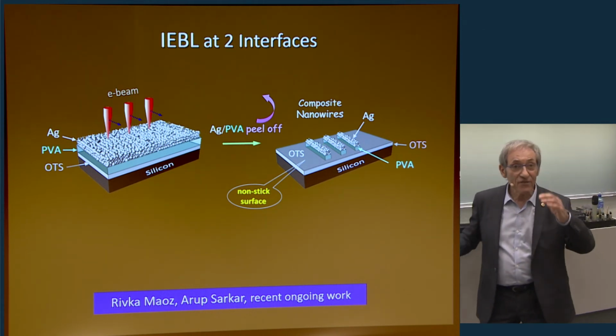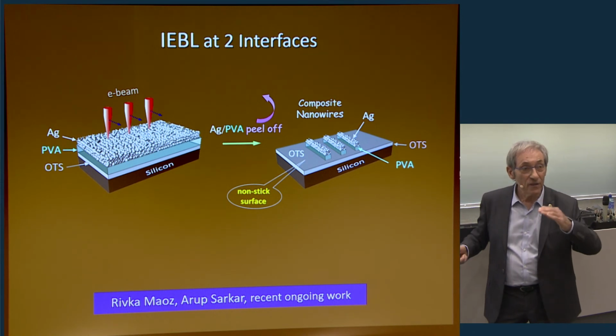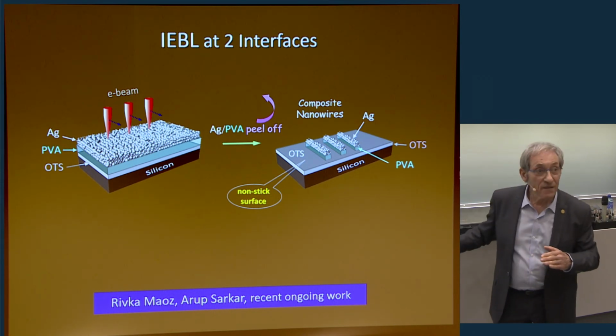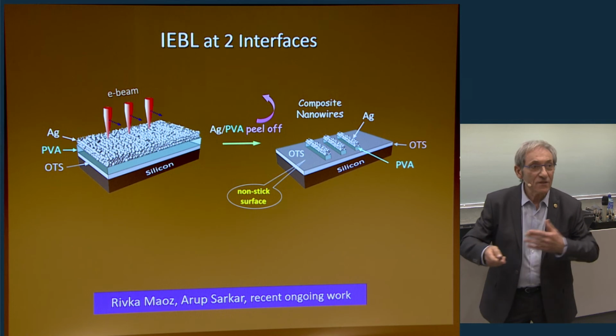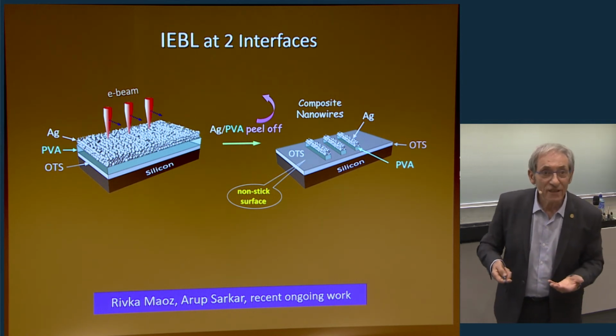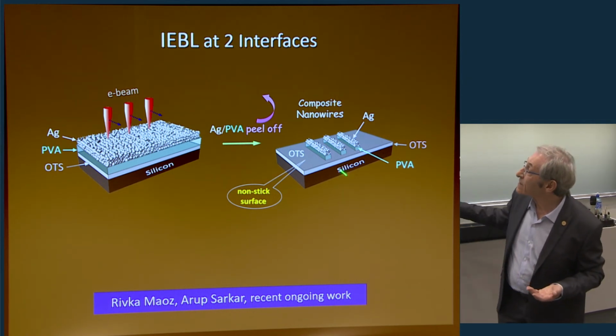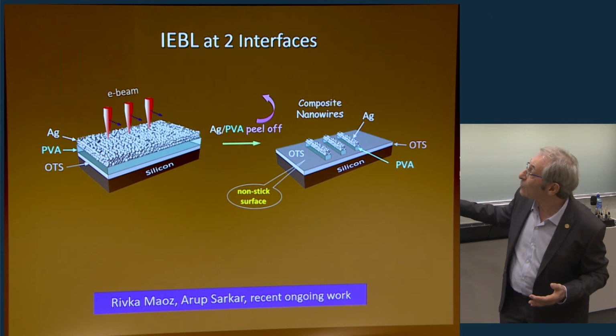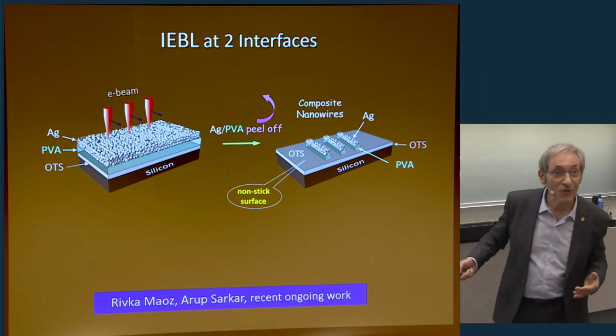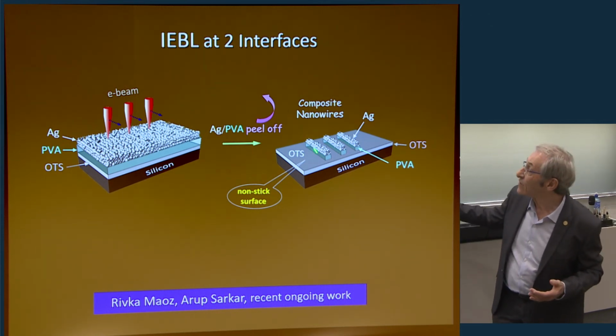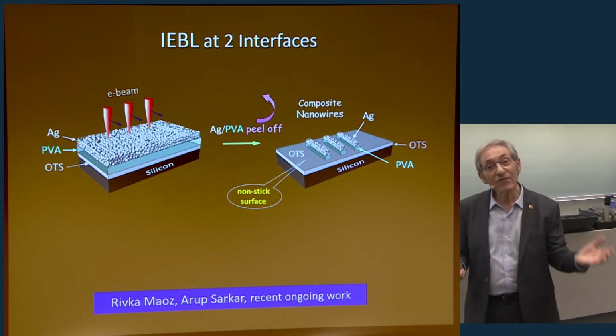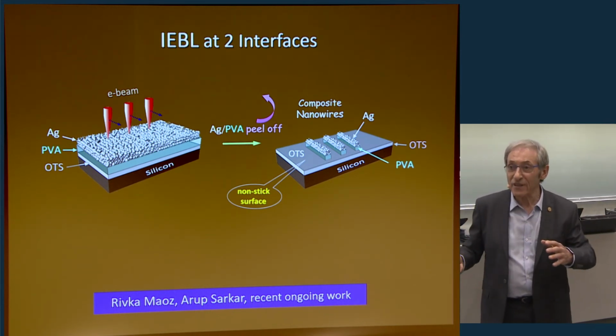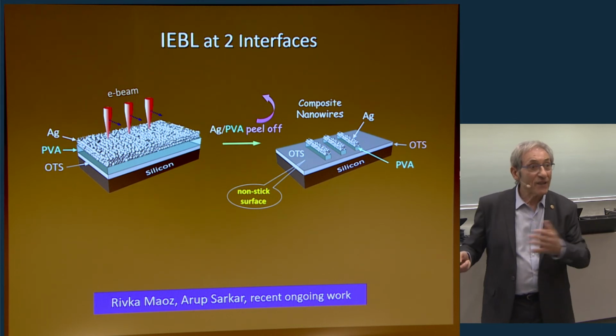So now we have silver on PVA on OTS. It's no longer just OTS because something changed there. And this is the only way that we can make what we now call composite nanowires, because we have silver and we also have the PVA. We can evaporate, we can remove the silver chemically and see what happens underneath.